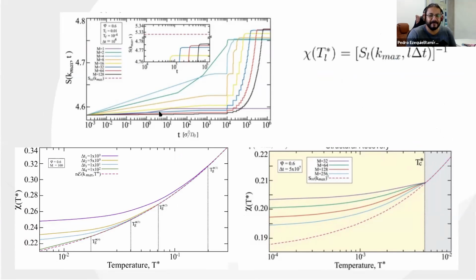It's a long discussion. It's about the Kauzmann paradox. Essentially, as I understand that, this deviation from the equilibrium from the glass solves, in some sense, this Kauzmann paradox, because if the system is relaxing to the equilibrium state, which is the supercooled liquid, then all the properties will have problems at zero temperature. So the glass, in some sense, solves the problem for the nature, of course, in the sense that it separates from the supercooled liquid line. But I'm not sure that we can say that the theory captures all these features in some sense.